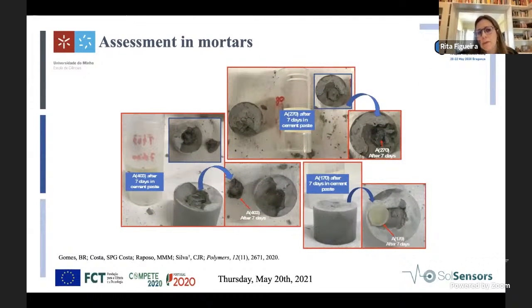Then we assessed the materials in mortars. The mortars were prepared with a water-cement ratio equal to 0.5. You can see that after 7 days, only the sample prepared with jeffamine THF 170, A170, showed good results. The others reacted or were completely destroyed due to the high alkalinity of the cement paste. So we started working only with jeffamine THF 170 and GPTMS.